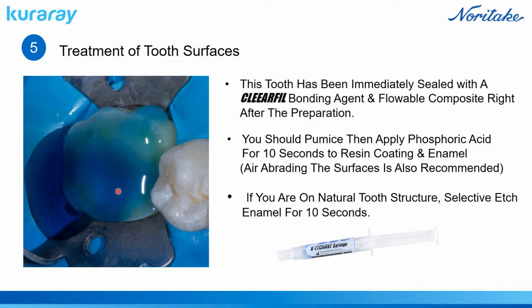Now, just so you know, this isn't a course on immediate dentin sealing and resin coating. The bond of his onlay onto this resin surface and enamel is 164% stronger than if you were to temporize the dentin and then come back and try to bond to it. There's been a lot of research on immediate dentin sealing for over 20 years. So this is a very proven technique that gives you a dramatic increase in your dentin bonds.